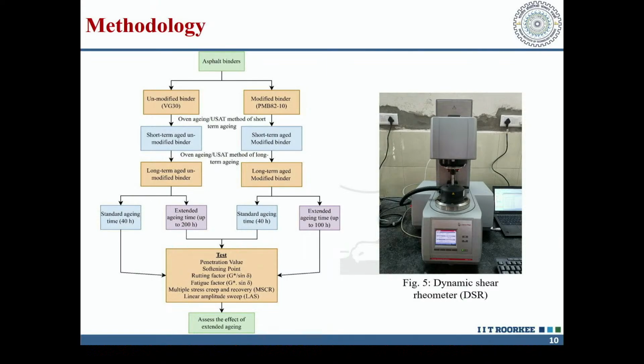We have taken, as I said, VG30, PMB 82-10, and short-term aging done for the VG30 as well as for the PMB 82. Then we have done both the agings using the USAT. And after that, we have done the aging for 40 hours, 150 hours, 200 hours for VG30 and 40 hours and 100 hours for PMB. And these are the tests which we have conducted: penetration, softening, rutting factor, that is G star upon sine delta, fatigue factor, that is G star into sine delta, MSCR, and linear amplitude sweep test, that is LAS. And after that, we have assessed the effect of extended aging.